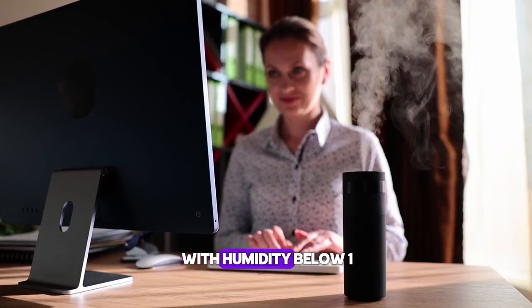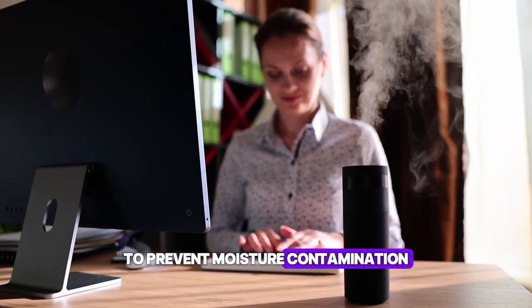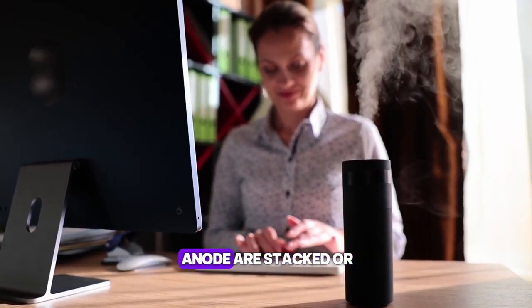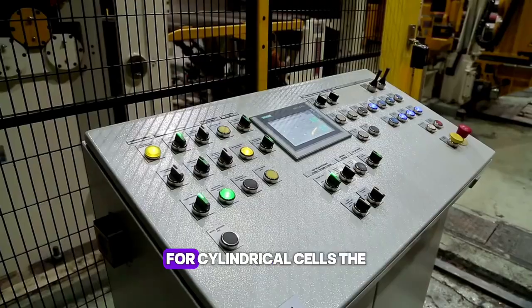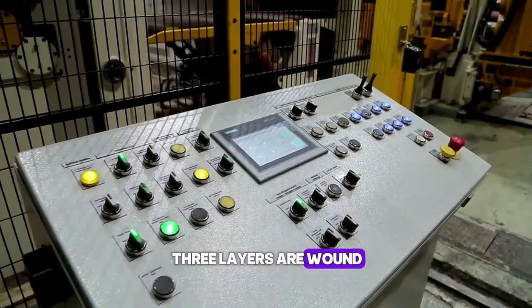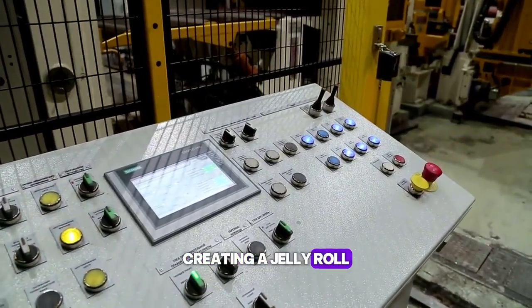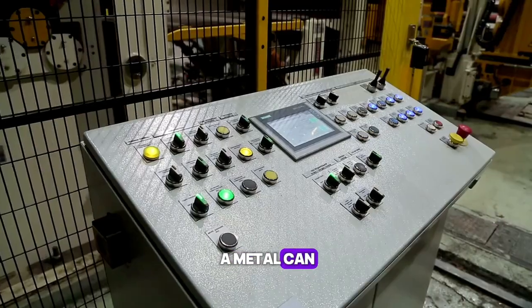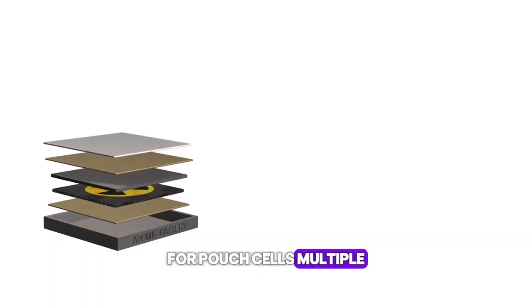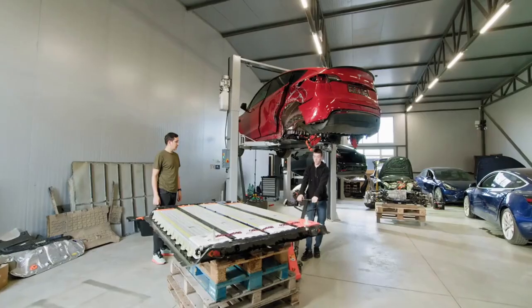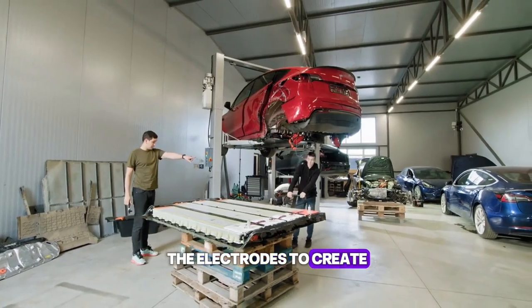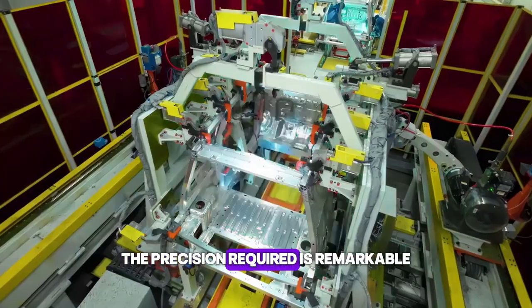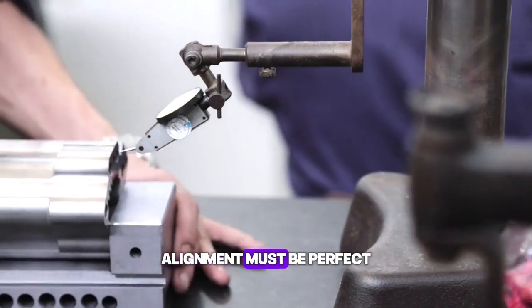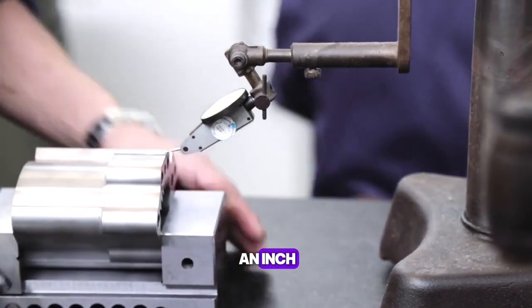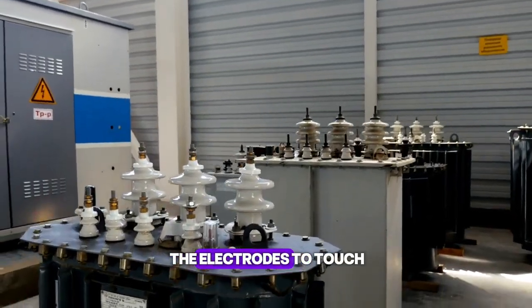In a clean room with humidity below 1 percent to prevent moisture contamination, the cathode, separator, and anode are stacked or wound together. For cylindrical cells, the 3 layers are wound into a tight spiral, creating a jelly roll structure that's inserted into a metal can. For pouch cells, multiple sheets are stacked in alternating layers. Tabs are welded to the electrodes to create electrical connections. The precision required is remarkable. Alignment must be perfect to within thousandths of an inch. Any misalignment could allow the electrodes to touch.